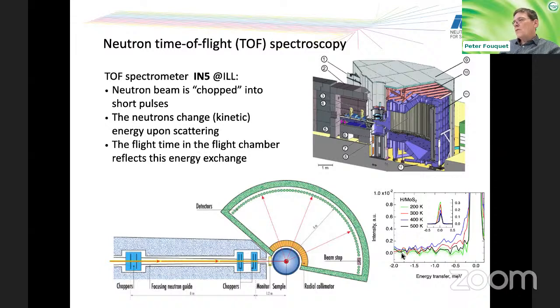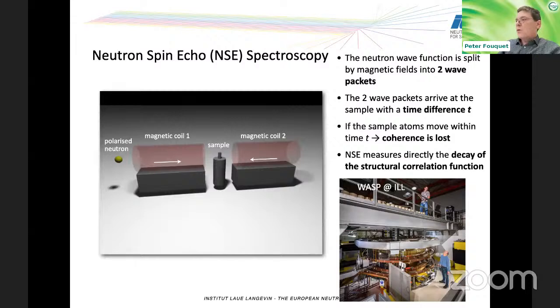And as a function of time, you see when the neutrons arrive at the detector. And arrival time can be recalculated into energy transfer, because time is related to a speed of the neutrons, and speed is related to the kinetic energy. And that lets us deduce afterwards if we have, for example, excitations, or if we have other diffusive energy transfers at the sample.